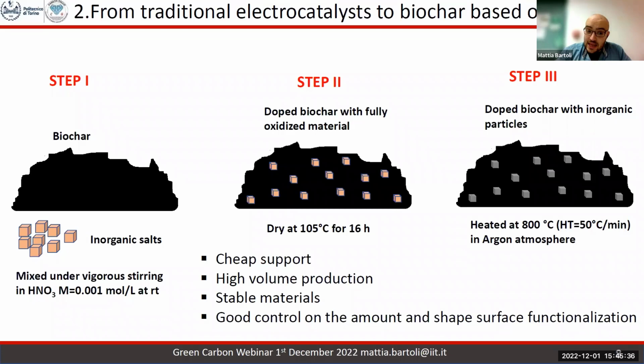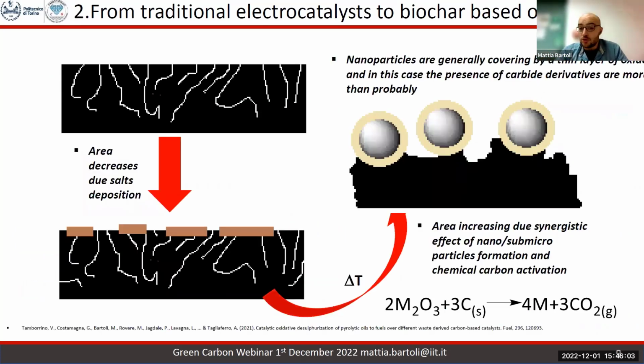But furthermore, we also use a more simple approach. We just impregnate the biochar with salt in a slightly acidic environment, and we reheat in the same furnace that we used to produce it, at 800 degrees, promoting a reaction that is commonly known as carbothermal reduction. It's basically the same process that is commonly used in metallurgical processes for the production of metals. So try to picture the biochar surface covered by a metal salt that is oxidized, and after that reduced by heating carbon, with the reaction that you can see at the bottom of the slide.